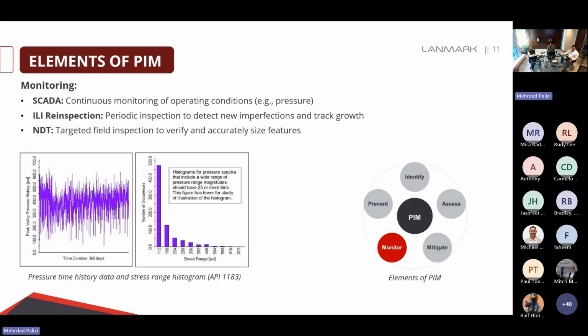Next, we have monitoring. This is going to be the ongoing follow-up component for integrity management. Operating conditions like pressure, temperature, and flow rates can be monitored continuously. But for most integrity threats, the monitoring is performed periodically. This typically is done through repeat ILI runs to identify new imperfections, and we can also track the growth of the known features. There is also non-destructive testing that is used to verify ILI findings, improve sizing accuracy, and at the same time, it could also be used when ILI capabilities are limited. So let's say if we have a girth weld for which we have a high demand of stress or strain, we can do the inspection over that with non-destructive testing.